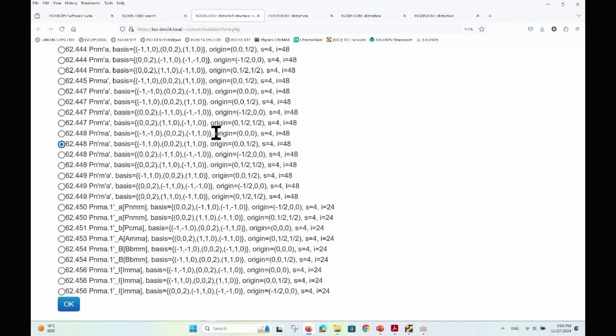You removed them from different places when you have a different origin shift. So same space group type, same category of magnetic space group, but the actual symmetry group is different. So origin shift matters. That's a subtlety that I think people often fail to appreciate, but it's quite an important one. So they look like the same symmetry group, but they're not because the operators were removed from different locations.